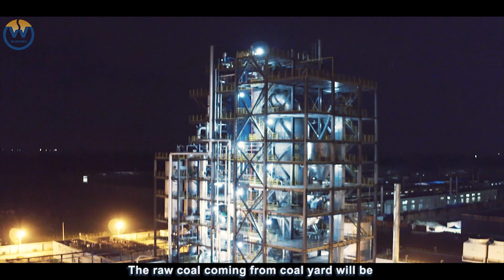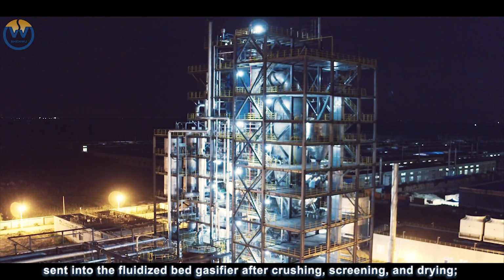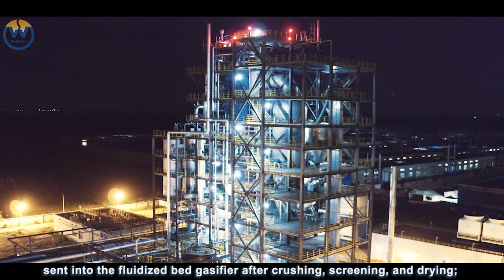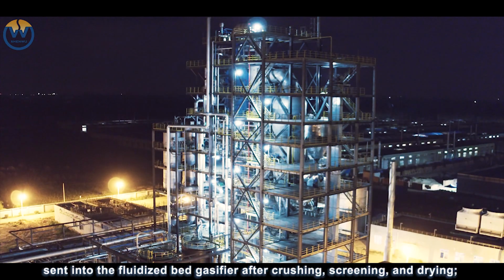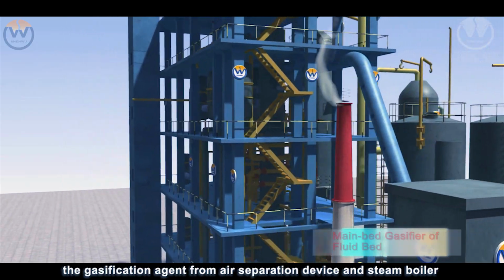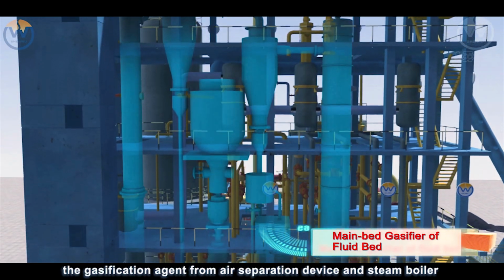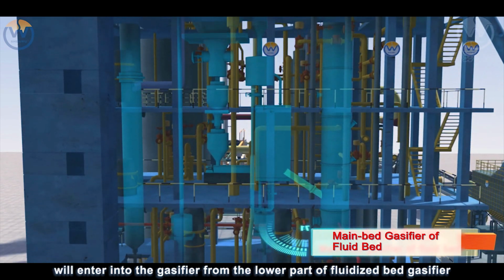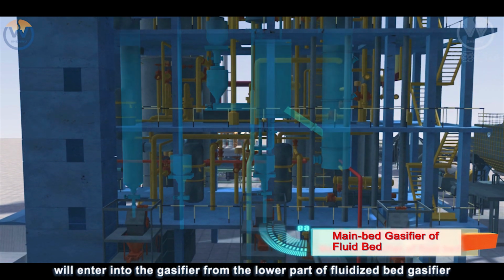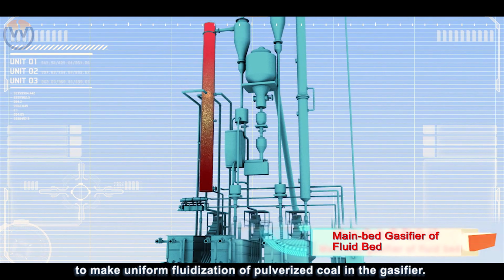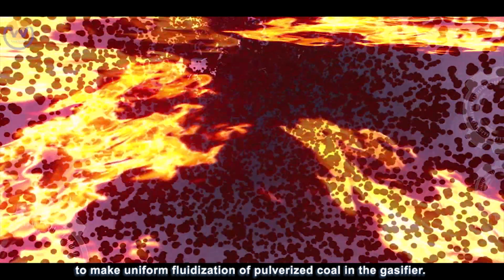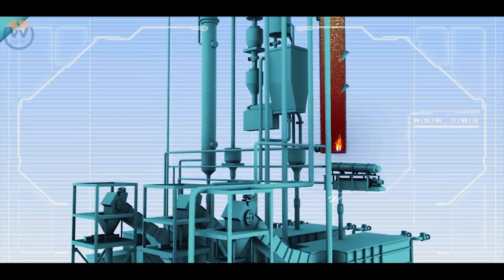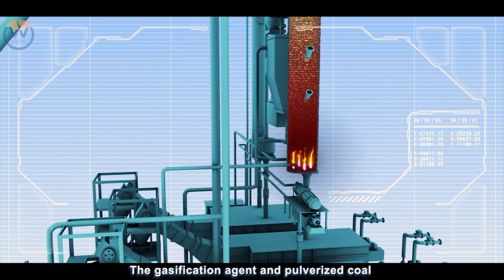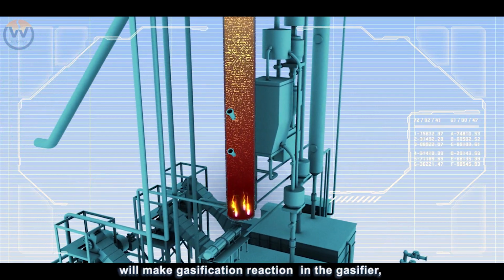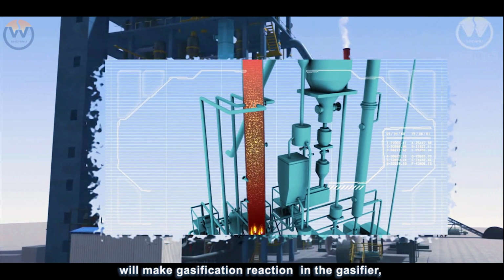The raw coal coming from the coal yard will be sent into the fluidized bed gasifier after crushing, screening, and drying. The gasification agent from the air separation device and steam boiler will enter the gasifier from the lower part of the fluidized bed gasifier to make uniform fluidization of pulverized coal in the gasifier. The gasification agent and pulverized coal will make gasification reaction in the gasifier.